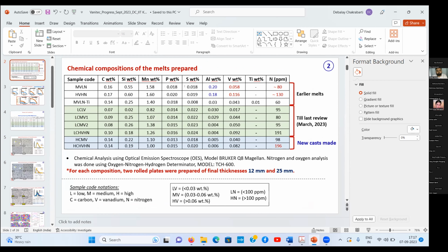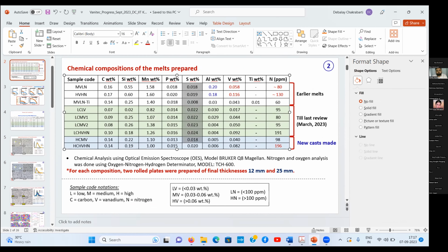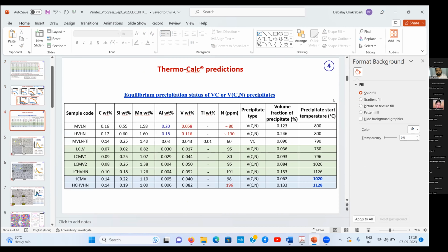Another thing is that the latest work that has been done on the high vanadium and high nitrogen steel. In that case, there was some issue with the furnace, as Devala told, and the grain size has come out around 18 micron. That's quite high. If you go to an industrial scale trial with the structural steel, the substrate we are expecting is roughly around 10 to 12 micron, and in all such cases that we are producing today, the grain size is in that range. If the grain size comes down, your toughness goes up, and if the inclusion level comes down at industrial scale, this will go up further. So once we go for the industrial scale trial, we are expecting around 60, 70, 80 joule minimum.